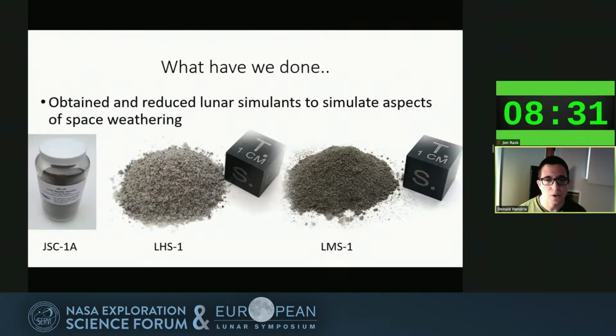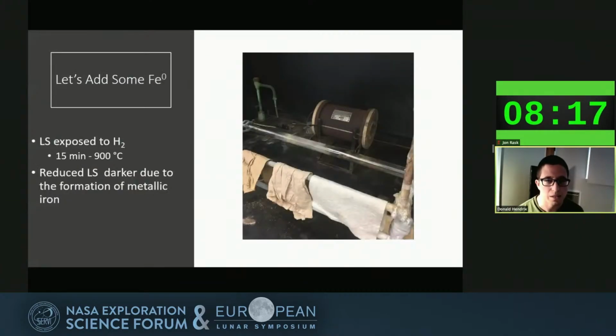So far we've obtained three separate lunar simulants: the traditional JSC1A, LHS1 from the Exolith lab, as well as LMS1 from the Exolith lab. Since these simulants by themselves do not have metallic iron, we try to add some. Basically, I take a little silica boat and add a little bit of the simulant sample, and that silica boat goes into a glass tube. This glass tube gets flushed with hydrogen.